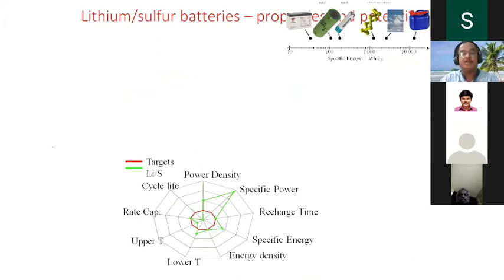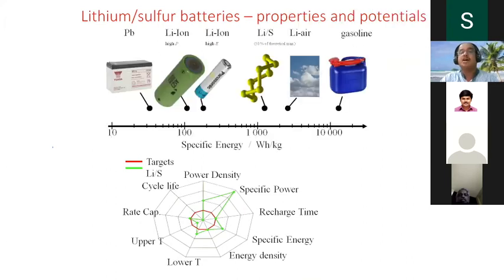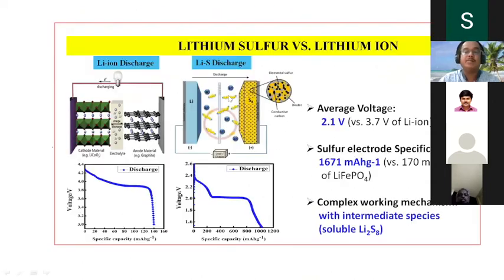You know very well that for lithium sulfur batteries, the energy density is almost unimaginable. So you can see here, 1000 watt hour per kilogram is possible. Moving from lead to lithium ion, to lithium sulfur. But people working in lithium sulfur battery realize how difficult it is. What are the major disadvantages? So lithium ion and lithium sulfur. The biggest problem is the complex working mechanism with intermediate species. That is the biggest bottleneck.